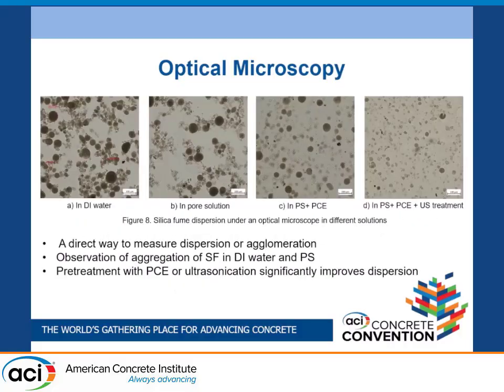The next test we performed was optical microscopy. It is a more direct way to measure dispersion or agglomeration rather than sedimentation. For optical microscopy, we use a Zeiss Axio Imager, putting a small drop of sample on a glass slide and observing it in the transmitted mode of the Zeiss microscope, and we saw these figures.